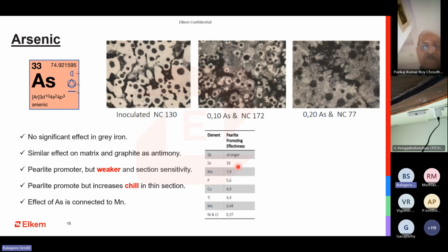So how do I handle arsenic if it is coming high from my trace elements, from my liquid metal, for whatever reason? For gray iron, I would not be that worried about it, because it can be highly sensitive to section thickness. So the definition of thin here is quite narrow. So that is not even considered for the typical operational range in gray iron. So you can run with arsenic. It's not a problem.